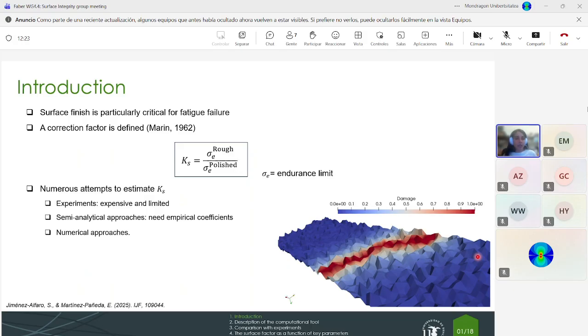And then we have numerical approaches, and here the most simple approach was when we approximate the surface roughness profile as a sinusoidal pattern, but the problem is that this is too simple because surface roughness in the end is not sinusoidal, it's not mathematically perfect. Or another approach that we have found is to use a Voronoi tessellation, but in this case we need to consider the grain size of the material that is not something very well known, etc.